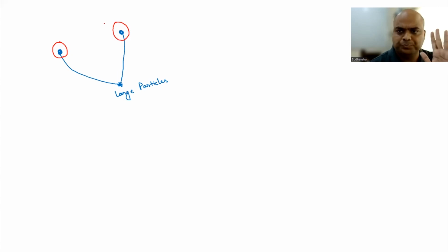And they are going to grow independently because of, say, the distance is larger. If the distance is smaller, then they are going to interact with each other, right? And now there is a strain localization between this region, right? In this region here, because of stress concentration, right?